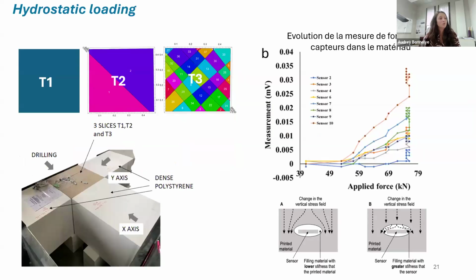So the idea was to 3D print, and so what we've done actually is to 3D print the first blocks. We've been 3D printing 3 different blocks from T1 to T3, one with no discontinuity, one with just one discontinuity, and one crazy one that looks more like a puzzle than anything else. And because the sample is quite big, it's a cube of roughly 50 centimeters by 50 by 50, and we want to drill inside of that sample, but it's too small to reach the borders of our machine. So we've been putting some dense polystyrene around it to decrease the volume of the machine.